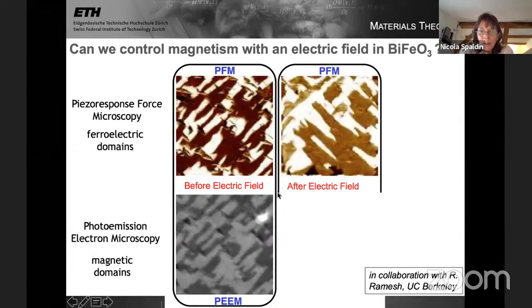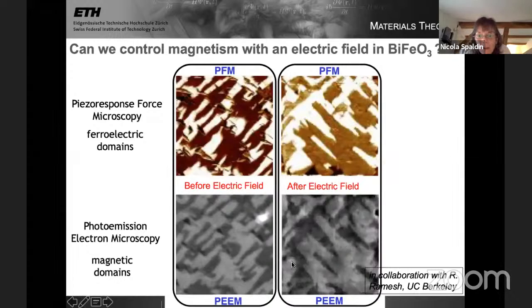Okay, so let me show you what happens when we apply an electric field. So this is after an electric field is applied, and in the piezo force microscopy, I want you to just see that we see something different. So domains have been switched. In this very first experiment, they were not switched very nicely or uniformly, but there's now a different pattern. And in the photoemission electron microscopy, they also switch, and they switch to the new pattern. So you see this kind of dagger here. And in particular, let's highlight maybe one spot that was white at the start and is now brown in the ferroelectric domains. And the same spot was dark at the start and is now light in the magnetic domains. So this was really very exciting.